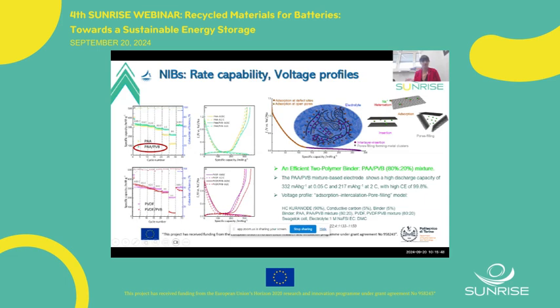That is very good. However, in terms of PVDF-PVB, the mixture shows worse electrochemical performance, the black one, especially at high C rate. So we can consider an efficient two polymer binder system, PAA-PVB 80-20%, that shows very good rate performance, also very good initial Coulombic efficiency.